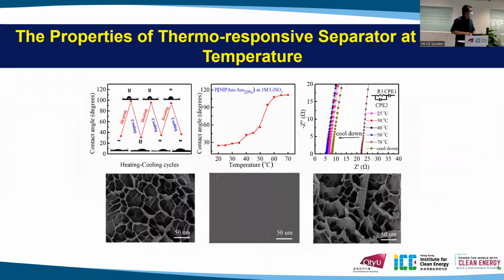And this is some characterization. We can see that at room temperature the hydrogel is hydrophilic, and when the temperature rises above the LCST, it becomes hydrophobic, and this is reversible. And you can see the resistance here. Here is an SEM at room temperature. We heat it to the LCST point and take the SEM. You can see that all the channels are blocked, and then we reduce the temperature. It is reversible.